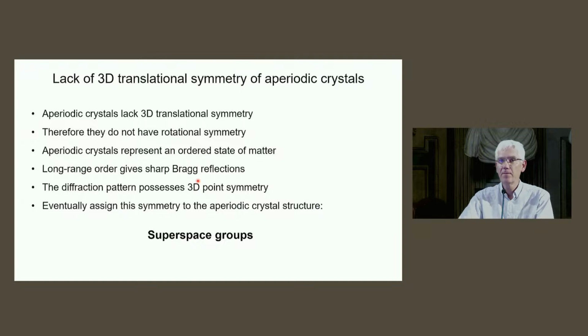As it happens, this diffraction pattern does have a point symmetry. The diffraction pattern exists in physical space, in 3-dimensional space, so it's a 3-dimensional point group. And there it's similar to periodic crystals, because also for periodic crystals in reciprocal space, the diffraction space, there isn't any translational symmetry anymore. We can index with 3 integers, but if we consider the intensities of the Bragg reflections, there is nothing to translate, and we observe a real point symmetry about the origin.